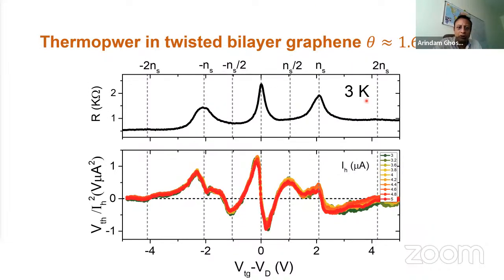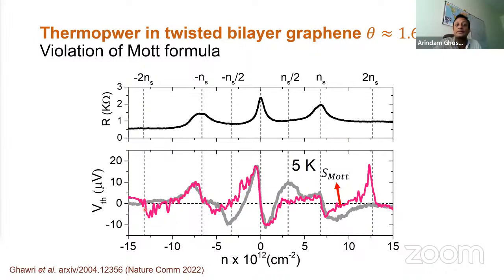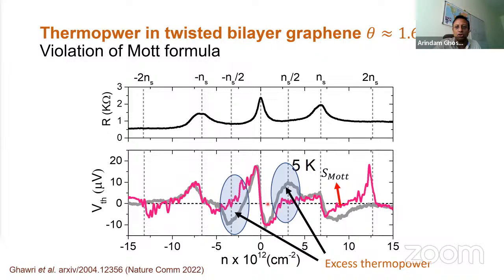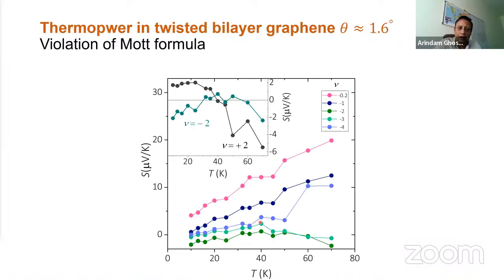Okay, so I'm going to compare this with the calculations from the semi-classical model. You can see the pink one is the calculation, and the gray color is the data. You can clearly see that it more or less agrees at most of the points in the Moire band, except when the filling factor is near half filling. And this is what you call an excess thermopower. Now, excess thermopower essentially means that there is, in some sense, an additional entropy of the system. And this entropy is not going to zero when you reduce the temperature, which is one of the puzzles that even systems like high TC superconductors have seen.